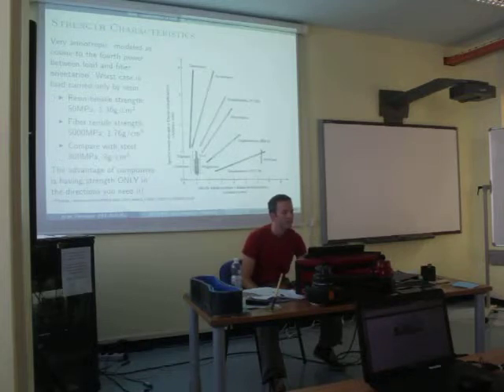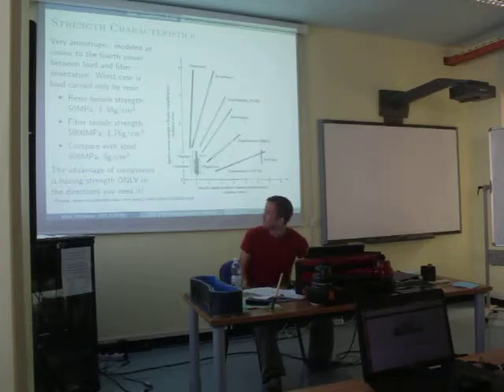So the tensile strength of a resin might be 50 megapascals, and it has a density slightly more than water. The fibers will be, say for carbon fiber, might be 5 gigapascals and a little bit heavier. Steel is 800 megapascals and about 8 grams per cubic centimeter. So you can see that this stuff is much stronger than steel by weight.